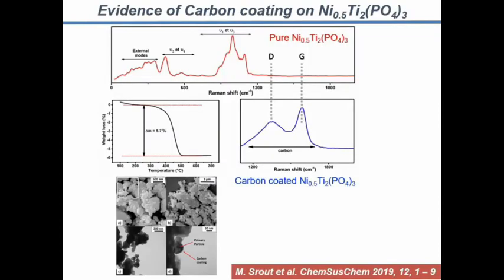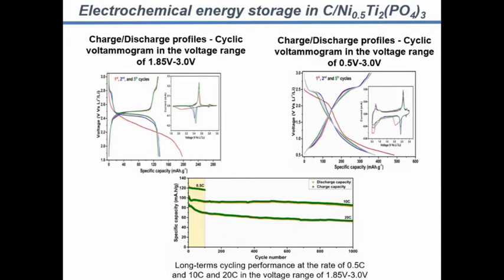So we would like to check if we really have carbon in our composite. We compare here the Raman spectroscopy of pure nickel titanium phosphate with carbon-coated nickel titanium phosphate. By comparison, we can see in the carbon-coated sample the existence of the D and G bands that are characteristic of the existence of carbon in the composite. The amount of carbon was deduced from TG analysis, which is around 5.7%. TEM and SEM clearly show that we have a carbon layer on the particles, which is the aim of our carbon coating. You can see more details in this paper with the reference in the slide. The second step is to use this composite as active material in a lithium battery in a coin cell.